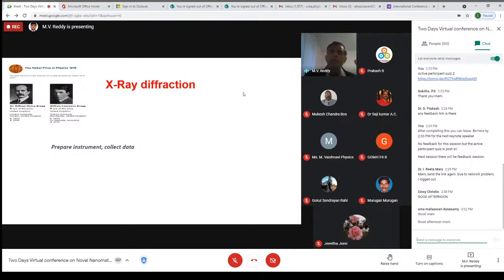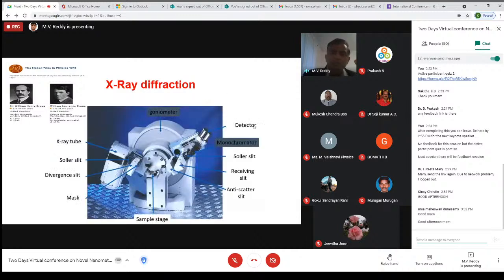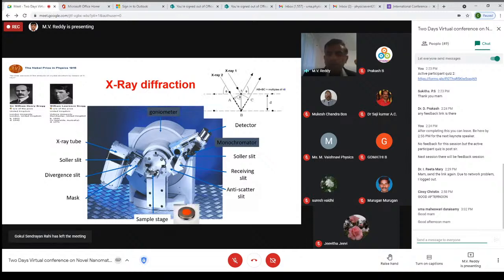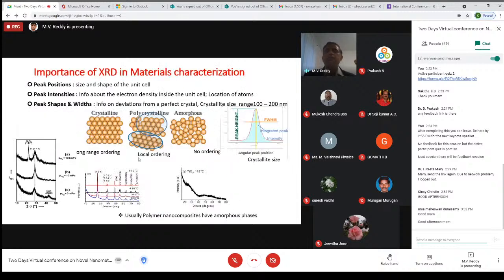So this is very important to remember: Bragg's law. For example, when X-rays are incident on a particular powder sample, which we are going to put here, diffraction occurs. This diffracted ray is collected by the detector. By knowing the well-known formula 2d sin theta equals n lambda, finally we get the intensity versus 2 theta patterns.